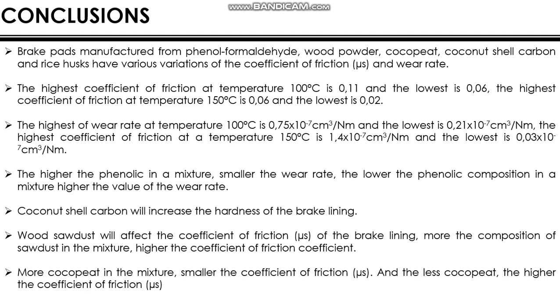The highest wear rate at temperature 100 degrees Celsius is 0.75 multiplied by 10 to the power minus 7 cubic centimeter per newton meter and the lowest is 0.21 multiplied by 10 to the power minus 7 cubic centimeter per newton meter. The highest wear rate at temperature 150 degrees Celsius is 1.4 multiplied by 10 to the power minus 7 cubic centimeter per newton meter and the lowest is 0.03 multiplied by 10 to the power minus 7 cubic centimeter per newton meter.